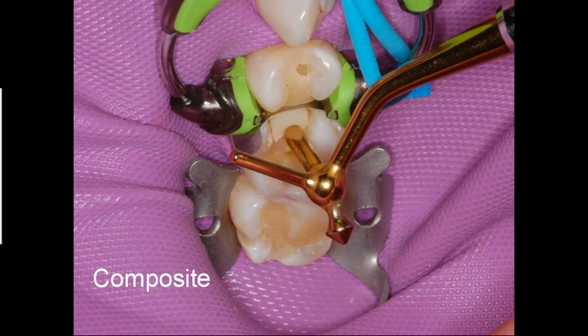Now we're going to go ahead using our multifunctional instrument. We're going to compress this, place this into the box first. If you're doing a multi-layer buildup or a 2-layer buildup, we're going to place a couple millimeters into the box first, fill it up a couple millimeters, cure that, and go on, and eventually end up with our enamel shade. This is the layered concept, and it's a very beautiful way of doing it. You'll see with using the bulk fill, this kind of eliminates some of the steps and some of the potential errors and incorporating some flaws and defects when you're starting to build it up, getting homogeneous buildup of that particular restoration. This multifunctional instrument is a nickel-plated titanium instrument and offers all the ability of 3 instruments in just one. So it really is a wonderful instrument to use.